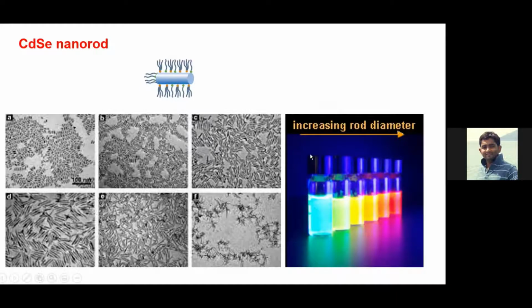When you increase the diameter of the rod, because the long part of the rod is already beyond the band gap regime, more than 10 nanometers, close to 20 nanometers, you can only change along one direction, like the z direction, the diameter of the rod. So the band gap depends only on the diameter of the rod, meaning electrons are confined in two directions. That's why you can get tuning of emission from different sizes of rod.